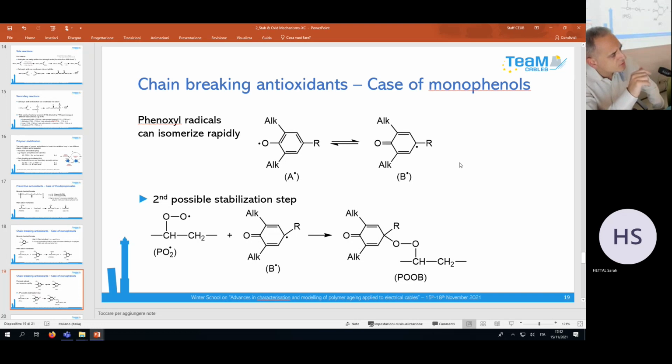And why do you ask this question? I have a question because we did some studies with some materials stabilized with Irganox and with Ostanox, so secondary antioxidant, and the carbonyl region of degraded material is quite different in that region. If you measure the absorption at 1710, 1470, 1715, and 1745, I think, something like that, the relative value of absorbance is quite different depending on the stabilization. So maybe, I don't know if that type of reaction may influence the value of the absorbance or not.